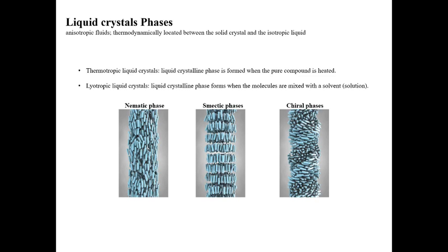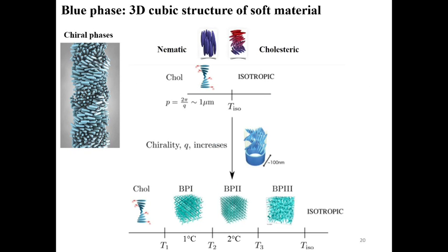In the nematic phase, if you picture each molecule as a rod, they orient in this way. When you add the chiral dopant, the molecules start to have the ability to twist. So it will start at one position, slowly twist, end up at another position, opposite, and continue until they resume the original position. That will be one period of the twist. So that is the cholesteric phase.